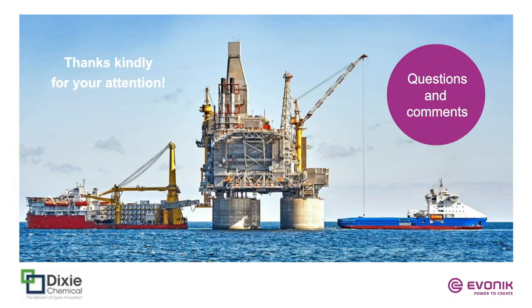Okay. Thank you. And is epoxy the best choice for syntactic foams? I'll start on that one. Is it the best choice? It is certainly the most popular choice. It has been used for some decades already. There's a significant use history. The thing about them, though, is that the focus has been on the rather simple side of epoxy chemistry using DGEBA resins, which seems to be perfectly suited for this application. So there's a good use history. There's a reasonable track record.